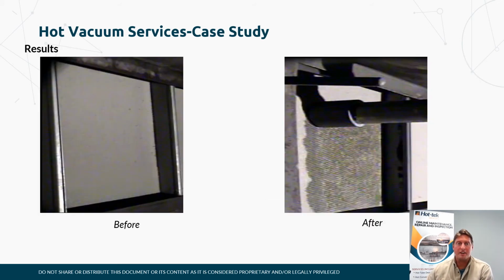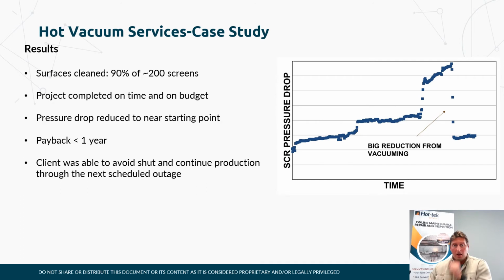This is the before and after. Of course, we can see the very heavy fouling on the left and the clean screen on the right. So roughly 90%, a bit more than 90%, for the roughly 200 screens that we were able to address. We saw the pressure drop, and we again see the final result of the SCR pressure almost identical to where we were at with startup and design.